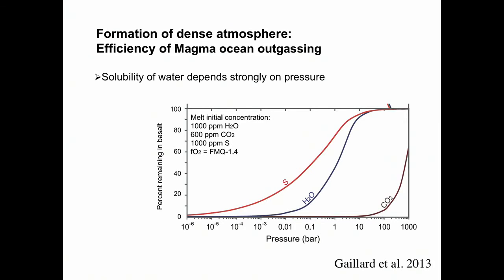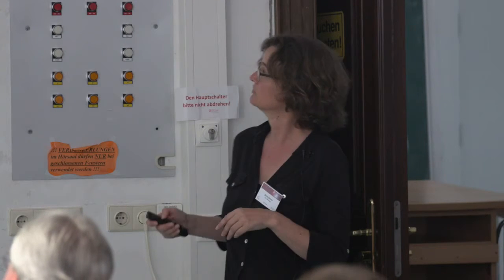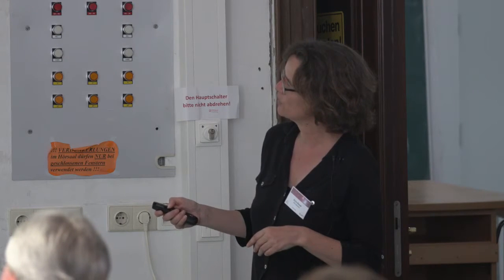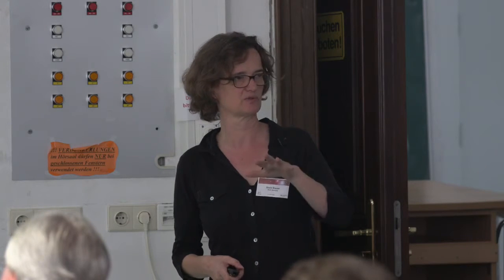Okay, now we come to the atmosphere. What we've seen so far is that we enrich the melt with water, which then is outgassed to the atmosphere. But how does it outgas? That strongly depends on the atmospheric pressure, actually. What you see here is the percent of water which remains in the melt or in basalt at the end, and this is pressure. We see this curvature for CO2 and H2O and also sulfur. The big difference here is for CO2: even at high pressure, the melt doesn't like to stay in the liquid phase, so it degasses. It is different for water. Only at low pressure does it degas more or less immediately, but at high pressure water likes to stay in the liquid phase or in the rocky phase.